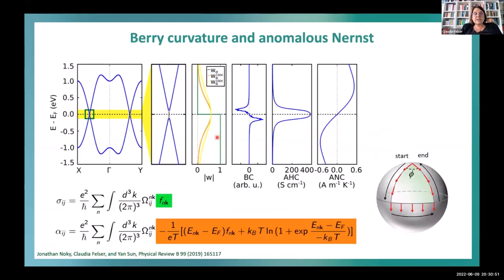Then we did toy model calculations, especially by Noky from my group. I said, look, let's understand. And he simply assumed that we have a crossing point in a simple band structure. It's much more simple. And then he applied spin-orbit coupling. He calculated the so-called Berry curvature, and you see it spikes here around the crossing points, okay? And then he calculated the anomalous Hall conductivity, and it always gives a giant response. And even the anomalous Nernst effect is a giant response. It's only a little bit more distributed over the energy scale, so it's not as sharp as the anomalous Hall effect. So this is maybe an experimentally interesting compound if one can measure the Nernst effect.